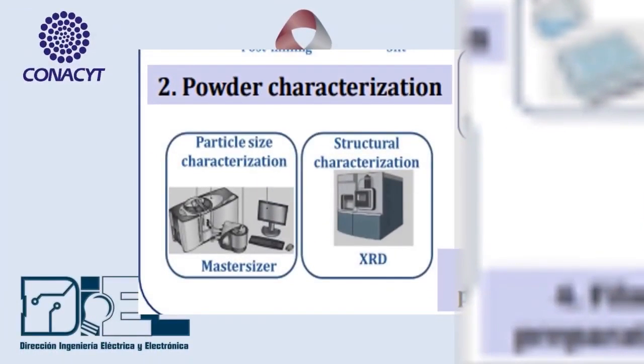The first step of this research involved the synthesis of NAGEL powders, which were fabricated following the methodology of our research group, which consists in a mixture of hydroxyapatite and bioactive glass powder using a high-energy mechanical milling. Then a sintering process is performed where the phase is obtained. After sintering, a post-milling process is carried out to homogenize the particle size. Finally, the powder is sieved to obtain a particle size below 53 microns. The powder obtained is structurally characterized by X-ray diffraction and laser diffraction to determine the particle size.